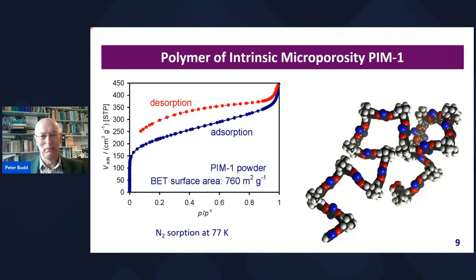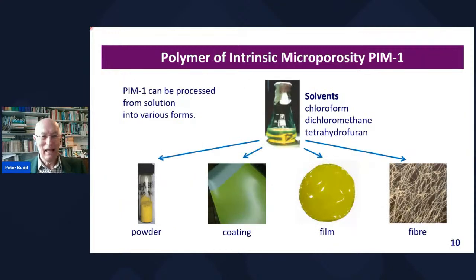even though it's a linear polymer, and even though, because it's a linear polymer, unlike a network, unlike a zeolite, unlike an activated carbon or any of these other microporous materials, it can be dissolved in certain solvents. Not necessarily the nicest solvents, but solvents like chloroform and tetrahydrofuran. And therefore, it can be processed from solution. So we had something which we could coat, we could turn it into a film, we could make fibers from it, and yet in the solid state, it behaved like a microporous material. It behaved in many ways like an activated carbon.